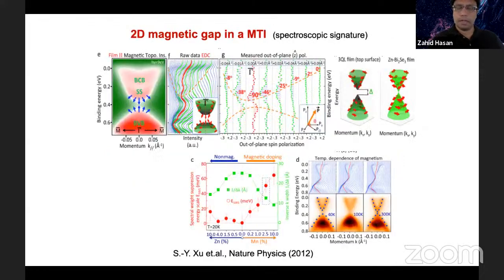So then we had to further explore the system with spin-resolved ARPES, look at the spin texture of the band near the Dirac node that is disrupted, and see what type of spin texture is realized. We introduced this idea that if we are using a thin film, this will also open a gap in the Dirac fermion channel, because now the top and bottom surfaces talk to each other. So there's kind of tunneling, and that will introduce a gap, but the spin texture is different. It's not this hedgehog type where, if you place the Fermi level here, you'll see a polarized surface Fermi surface. That is not the case.